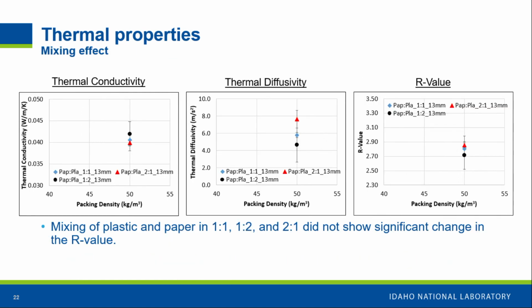So when we mix them together in different ratios, we wanted to see, for example, as on the conversion side, sometimes if you mix A and B, you might get some sort of synergistic effect on the product. We wanted to see whether mixing paper and plastic changes our thermal properties or not. But we didn't see that much change in the thermal properties, especially the R value, because previously we saw that even mixed plastic or mixed paper have a similar R value. So they behave the way we mixed them.